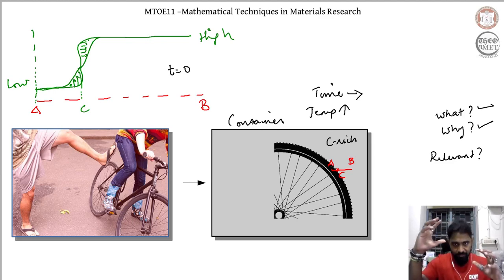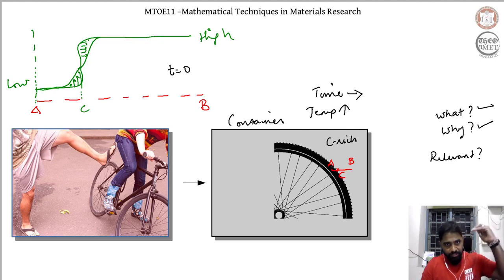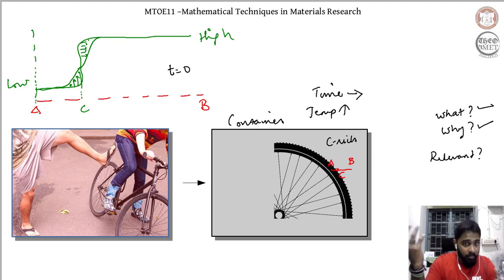And when I increase the temperature and hold my system at high temperature, the carbon wants to reduce this disparity. The carbon moves from high carbon concentration to low carbon concentration, meaning the carbon moves from the surrounding to my rim. So as the carbon concentration decreases in the surrounding, the carbon concentration increases in my rim. So this is what dictates the increase in the carbon concentration within my rim.